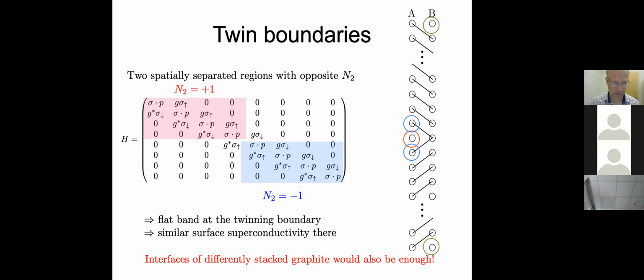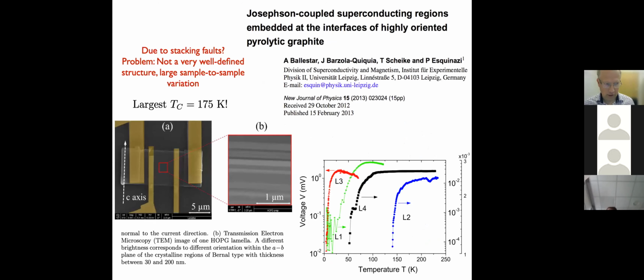In fact, you could also realize superconductivity in such systems not as a surface state, but as a kind of thin boundary state. If you have rhombohedral stacking and then make a stacking fault, you would also have a localized state there, and you could study what happens to superconductivity there. There is some evidence of possible superconductivity in such systems where you have stacking faults.